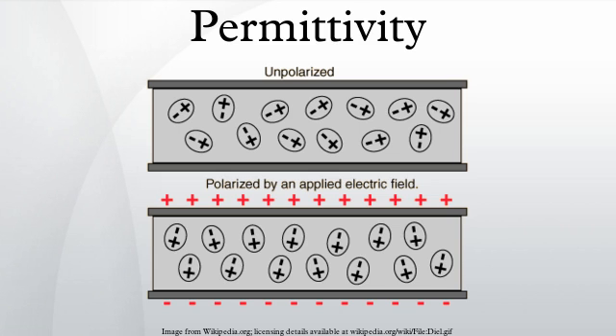The above effects often combine to cause non-linear effects within capacitors. For example, dielectric absorption refers to the inability of a capacitor that has been charged for a long time to completely discharge when briefly discharged. Although an ideal capacitor would remain at zero volts after being discharged, real capacitors will develop a small voltage, a phenomenon that is also called soakage or battery action. For some dielectrics, such as many polymer films, the resulting voltage may be less than 1 to 2 percent of the original voltage. However, it can be as much as 15 to 25 percent in the case of electrolytic capacitors or supercapacitors.